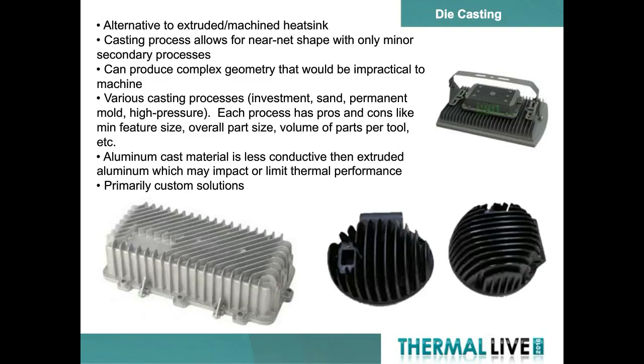Downside of a die casting is that the material is porous because of the way it is formed. This can impact the thermal performance. What we've seen is based on the alloy that's chosen, you can have thermal conductivities between 80 and 170 watts per meter K compared to an aluminum extrusion at 200 watts per meter K.